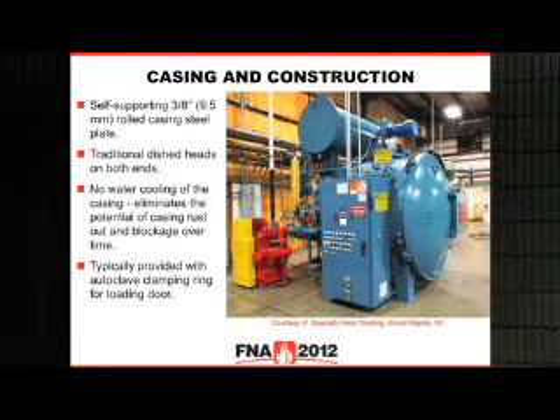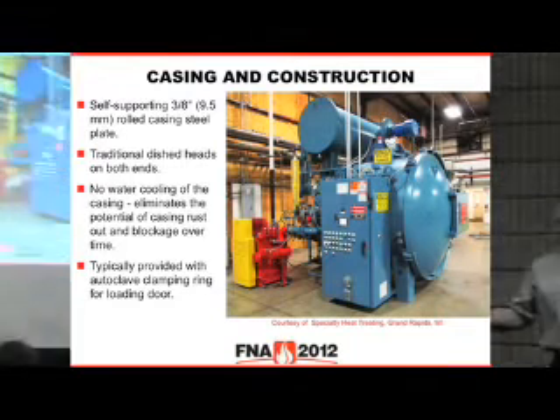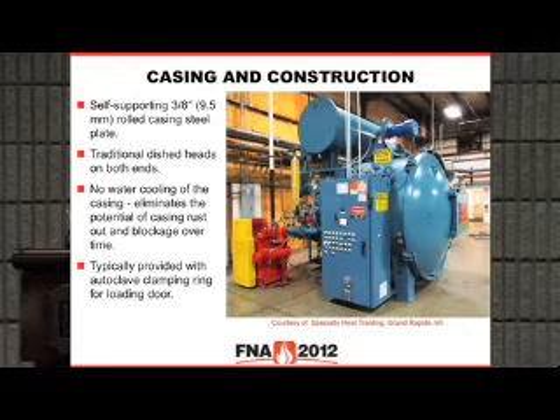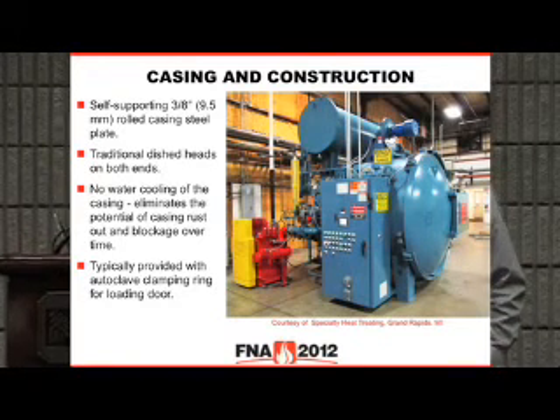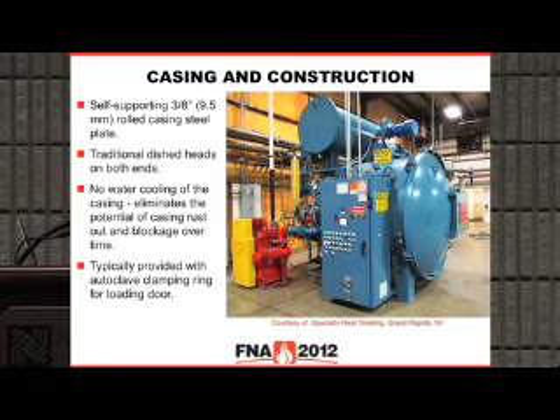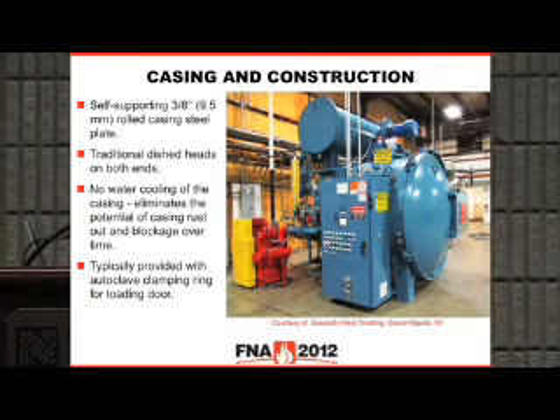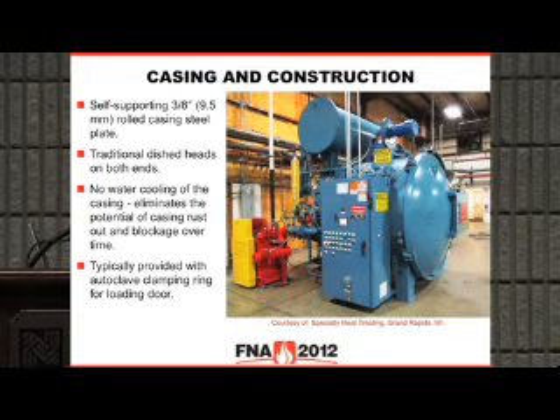How are they put together? Traditionally, it has a round casing that's rolled. We roll it from 3/8 inch steel. The back of the furnace has traditionally got a welded dished head. Again, this is single wall, so there's not a water jacket in it. When you get into water-cooled casings, water system maintenance is the best thing you can do in keeping that water always flowing. The worst thing you can do is shut off a water system to a vacuum furnace and just let the water sit in there and stagnate. Treat the water, keep the pH levels up, flush it, have rust inhibitors added to your water, and you can get 30 years, even 40 years of vacuum furnace life. We build them without a water jacket, so all of those corrosion issues just go away, and that ends up making this furnace one that will last for decades and need very little attention.